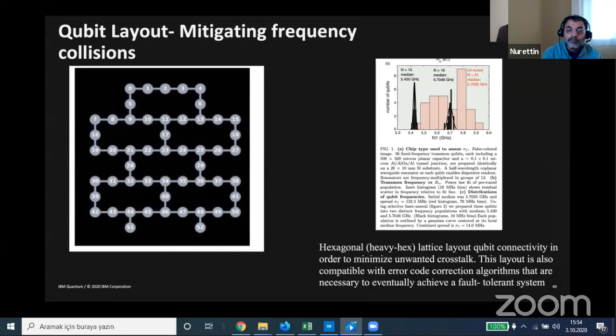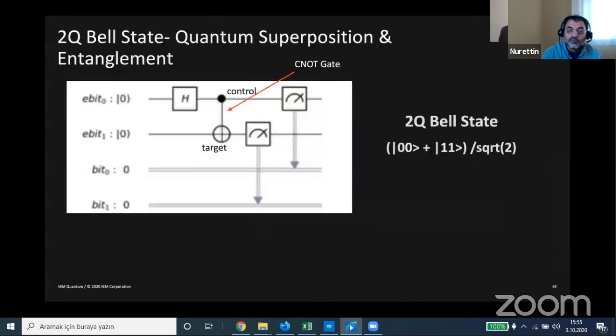And as shown here, we were able to shift the frequency into 2 clusters. We can achieve these 2 clusters. And in addition to shifting the frequency, this data shown here in black, we enhanced our process to reduce the variations in the Josephson junction. So given these improvements, we can then increase the number of qubits, and also we can improve their connectivity and hence improve the quantum volume without incurring the frequency collisions.